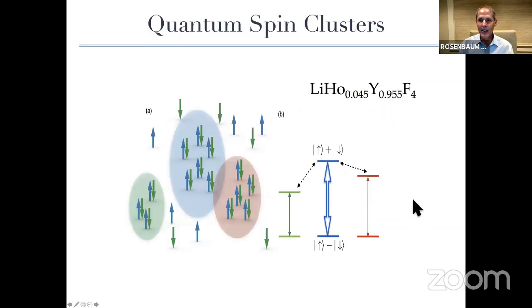Okay. So this is our picture. We have these spin clusters. You can label them by frequency in the sense that if I drive this at different frequencies, I pick out different size spin clusters. And then I can excite them out of their ground state, which gives you the hole because they're no longer responding when I'm twiddling them with that small field. So I have this excitation spectrum, and they're interacting with other excited clusters, but they're also interacting with non-resonantly excited clusters that are close by. So I have excitations up into the higher energy state, which tends to be more fully magnetized, and then various pathways that they can relax. And it's the coherence and the interference between these pathways that gives you the Fano line shape.